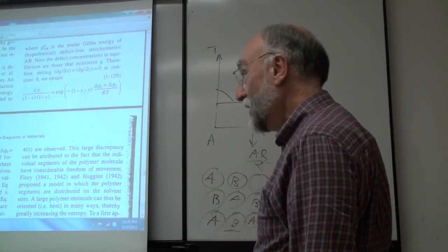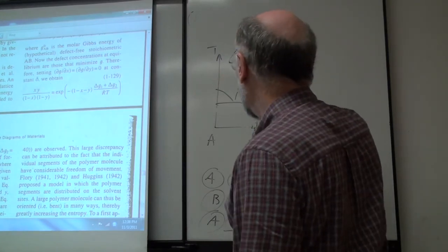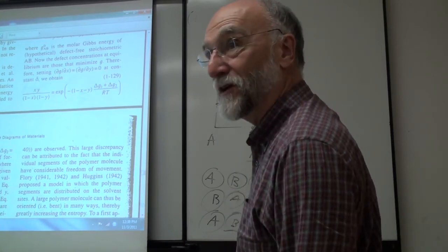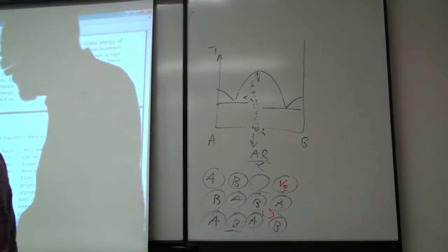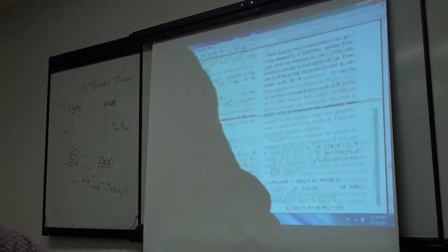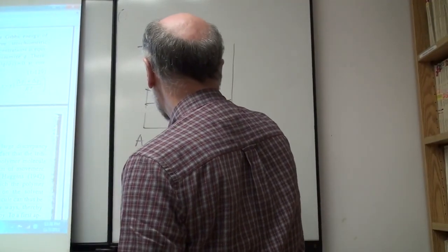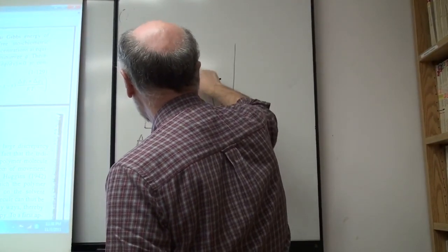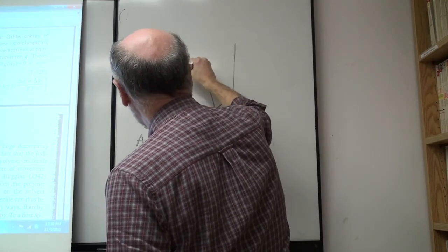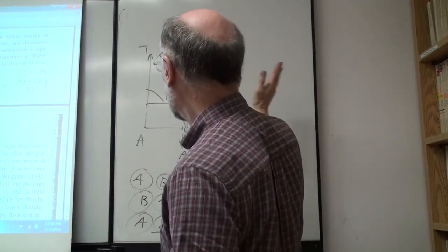So you measure it at the stoichiometric composition at lower temperatures. Or you can measure it at higher temperatures, but we'll measure it at 50-50 if you possibly can, at the actual stoichiometric composition. I might point out, I think I pointed this out before, you can have a compound that can narrow down to 50% exactly, but is much wider on one side than the other, so that when you go up to high temperature, the actual maximum, the congruent melting point, can be significantly shifted to one side. That doesn't mean the compound isn't 50-50, it means that the defects on one side are much easier to put in than they are on the other side.